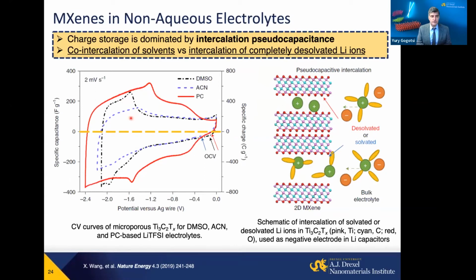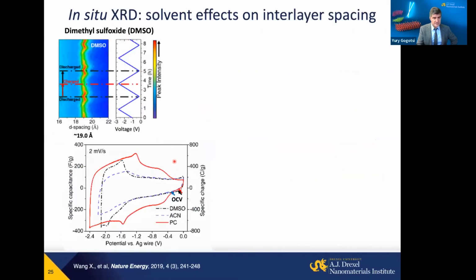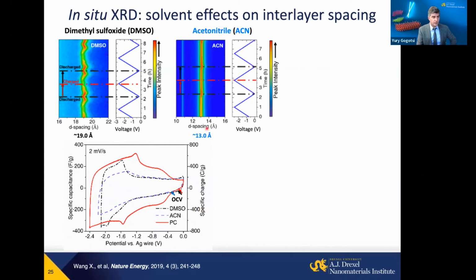Similar differences we observe if we look into organic electrolytes. Some type of a lithium TFSI electrolyte, type of electrolyte used in batteries here. What we found was again that depending on the solvent we use, we can get different electrochemical performances related to either intercalation of electrolyte and solvated ions, like in case of DMSO with lithium, and oscillation of lattice spacing as intercalation happens here. Or much smaller changes here, 19 angstrom, 13 angstrom.